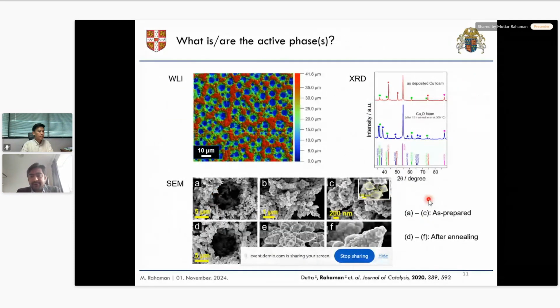If we really want to monitor the active phase of the carbon dioxide conversion process, or the active phase of the catalyst while it is doing carbon dioxide conversion, just a brief idea I wanted to share with you here. Let's say we use a copper oxide material just for the multi-carbon alcohol production we saw. If we use copper oxide under the carbon dioxide conversion process, this is a cathodic process, a reducing environment, the copper oxide itself will reduce into copper zero.